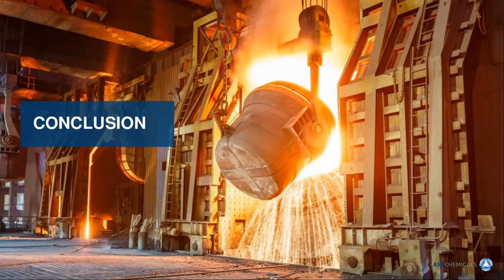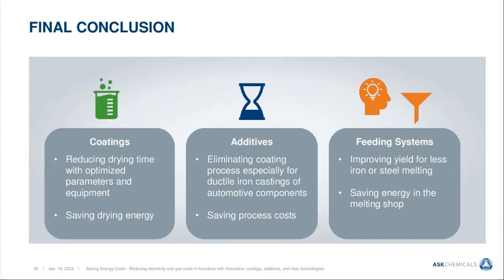So, the conclusions of this webinar today about how to reduce energy with these products. Let's remember about coatings. We can reduce the drying time with optimized parameters and equipment, and this will give us savings in energy in these drying operations. Talking about additives, we can try to eliminate the coating process, especially for ductile iron castings of automotive components, and this will give us also these savings. And talking about feeding systems, both risers and filters can also help us improve our yield. We can also save some metal, and in the end, we save energy in the melting shop.